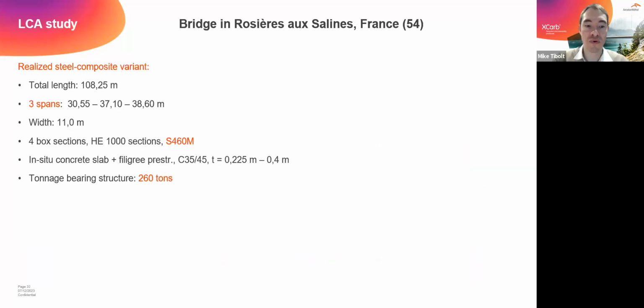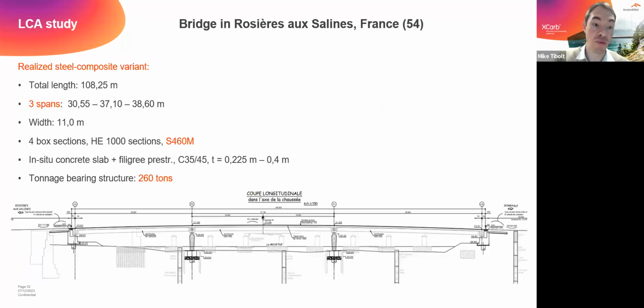So for the variant, of course, the total length remained the same. However, by switching from pre-stressed concrete to hot rolled sections in composite, we could gain 1 span. So we came down from 4 to 3 spans, as you can see. The width of the section remained, of course, the same. And what did we use for sections? We used hot rolled HE sections that we weld to a box. So we had 4 box sections in S460M.